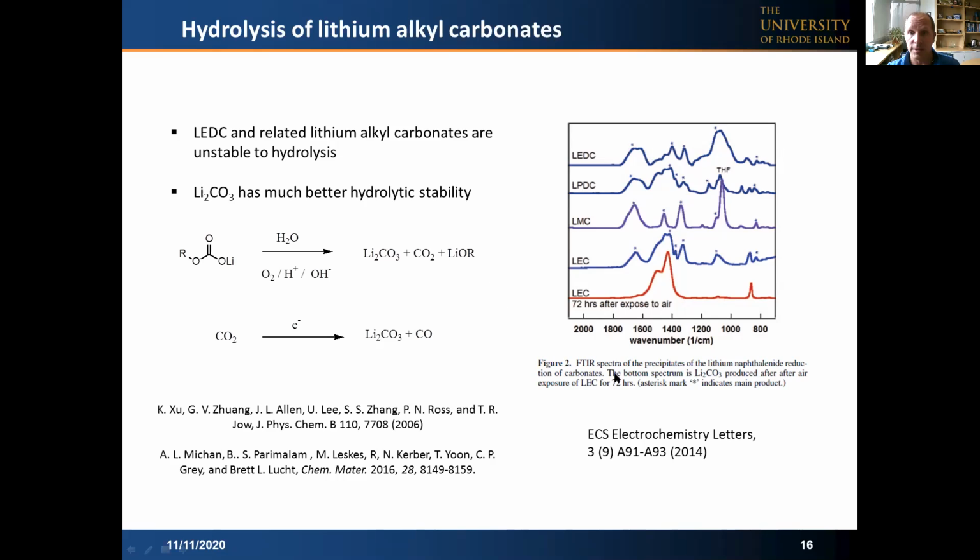And if we take these species and expose them to air, water vapor for a very short period of time, the IR spectrum that are characteristic of these lithium alkyl carbonates rapidly changes to lithium carbonate after a very short period of time. So what this suggests is that these lithium alkyl carbonates are relatively hydrolytically unstable. And upon exposure to water, they're converted to lithium carbonate, CO2, and lithium alkoxide. This has been previously reported by Xu and Zhuang in 2006.